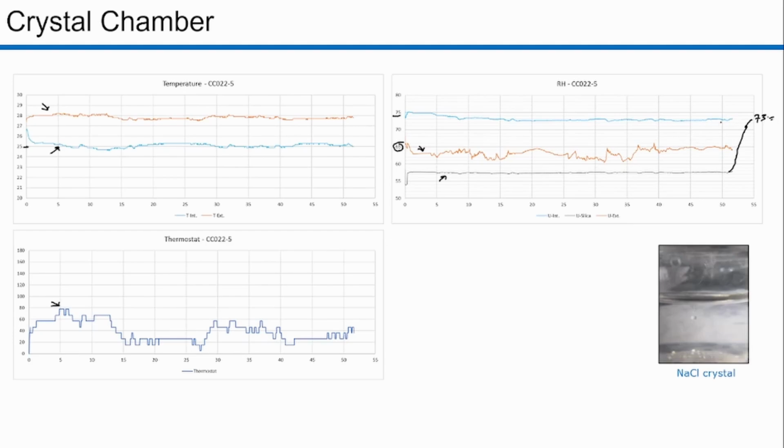be able to remove water from my solution, so I have to reset the silica, put new silica in the chamber. We can also see that the solution started near the equilibrium point, and then it slowly went down to near 73%, where it stayed over the course of like 50 hours in this series.